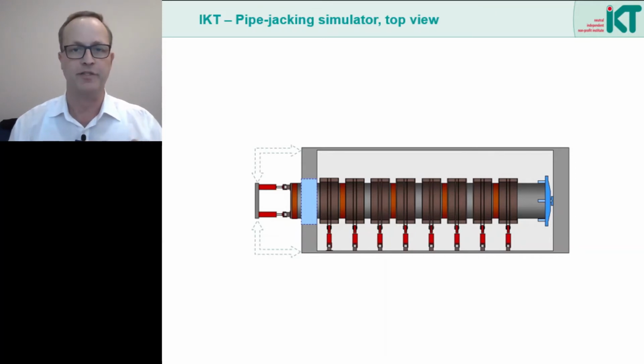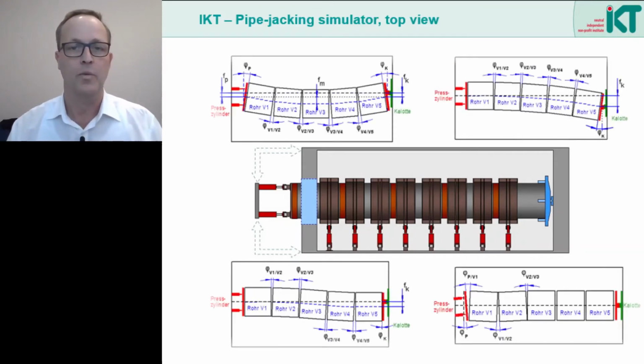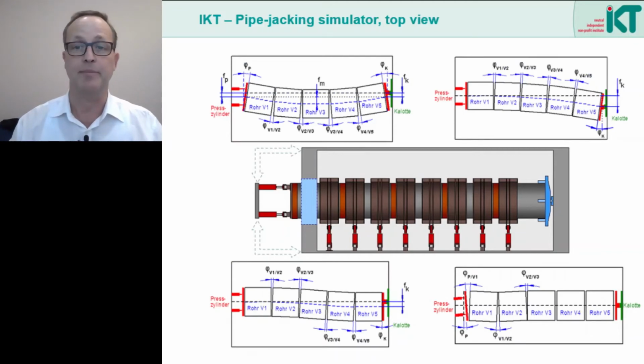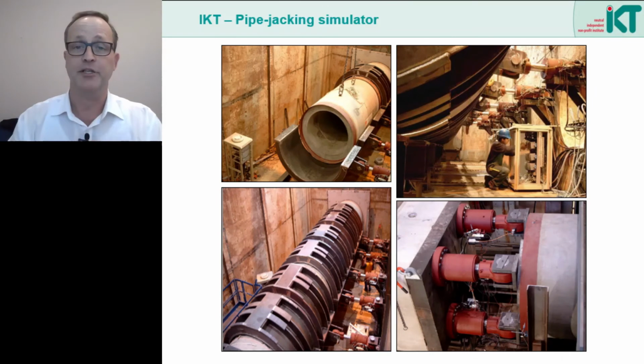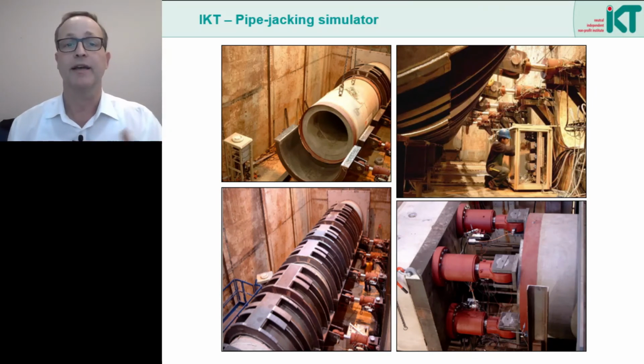And this makes the purpose of the whole thing very clear. With the horizontal jacks, the pipes can be positioned in such a way that we can simulate all important pipe jacking conditions in the test stand on a scale of 1:1. This also means that we can traverse the sample route again and again in the same way and compare the results, for example for different types of pipe or different pressure transmission rings. After all, this is not possible in practice because the soil conditions in the route of the pipeline vary from side to side.